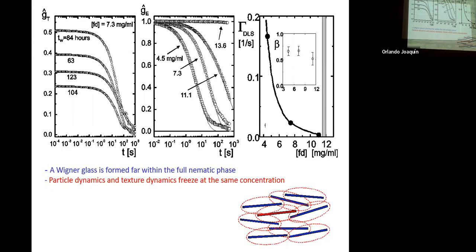The particle dynamics freezes at the same concentration where the texture freezes, and that makes almost sense: because if the particle dynamics freezes, the domains become larger, they become solid, and of course then the dynamics of the texture will also stop, freeze. That is the intuitive explanation of why you find freezing of the particle dynamics and texture dynamics at the same concentration.